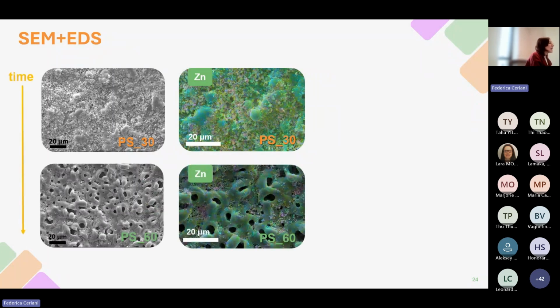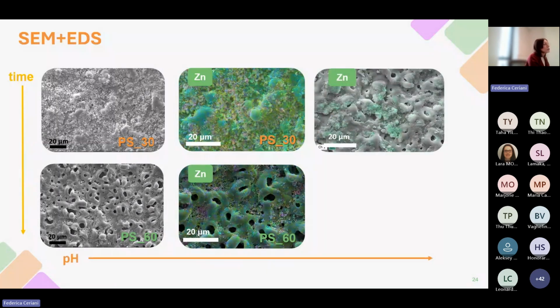So the sealing effect is negligible in this case. If we directly compare the morphology of the PS30 sample with the one obtained for the PS60 sample, it is evident that lamellas almost completely disappeared. But if now we compare this sample with the one produced after 30 minutes of immersion in the sealing bath, but working at a pH equal to 7, we could note that its morphology is quite similar to the one obtained for the PS60 sample. And this suggests to us that the pH of the sealing bath decreases over time during the post-treatment.